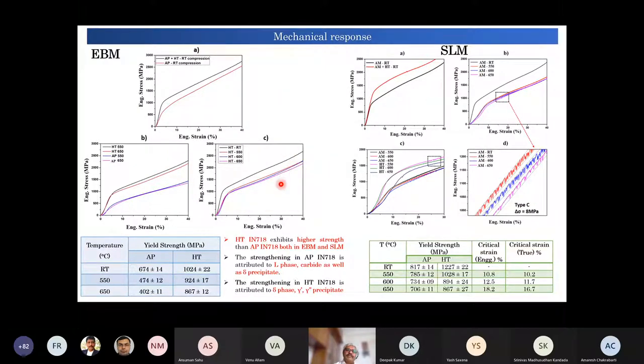For example, in this case, after heat treatment, there is a difference in the AM product. You could see here, as printed and heat treated once, these two are heat treated. So heat treatment brings a lot of changes in these materials. And a similar response was seen for both the EBM and SLM. Of course, the degree was different. And there were some other finer features which were a result of faster cooling in the SLM process than the EBM process.